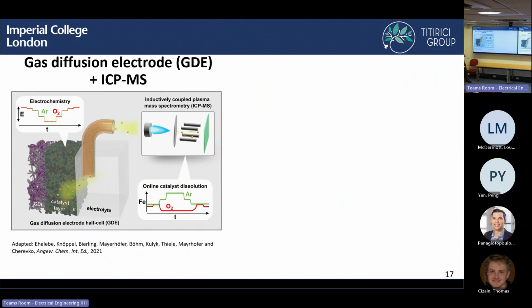And so what you can do here is use a gas diffusion electrode system. So this is much closer to mimicking a real fuel cell. So in this system, you'll have your oxygen or argon flowing along the backside directly, which can contact the catalyst layer. So you can end up with much higher current densities because you're not dissolving the oxygen in an electrolyte. You can ideally access the site directly. So you have your argon or oxygen on the backside, your catalyst layer here, and then you have an electrolyte where your ICP-MS is then withdrawing sample over time, and you're analyzing the metal concentration in that electrolyte.